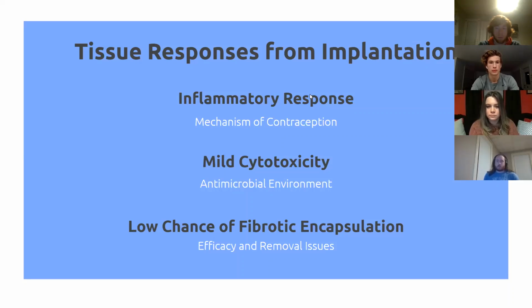The device will also create a mildly cytotoxic environment using the antimicrobial and antibiofilm properties of silver nanoparticles. Too much silver can cause high cytotoxicity, which can damage the endometrium. However, this is seen only at doses at or above 100 micrograms per milliliter, which our device will fall well below. But the cytotoxicity will still be evaluated according to ISO standards.